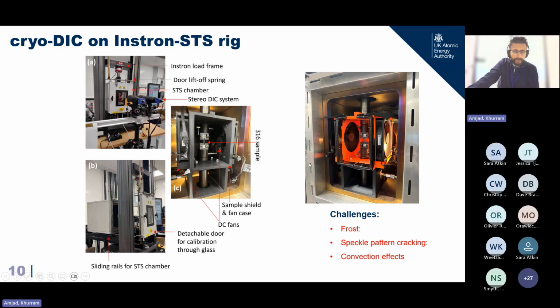So the Instron STS rig that we have, we have spent a significant amount of time trying to deploy DIC on it, and there are some challenges with it. The first is because it's not a vacuum chamber, we have an issue of frost. The way it works is that it has the inlet for liquid nitrogen, which by the time it comes to the chamber is in a gaseous form, and there is a fan at the back which circulates this cold gaseous nitrogen into the chamber. So you get convection effects, which affects your optical measurements. So that was a challenge.